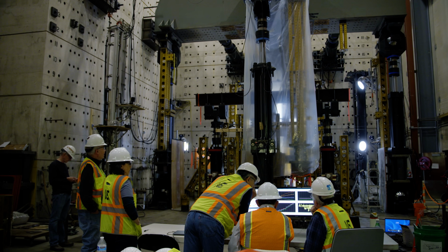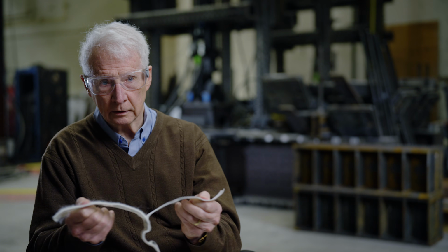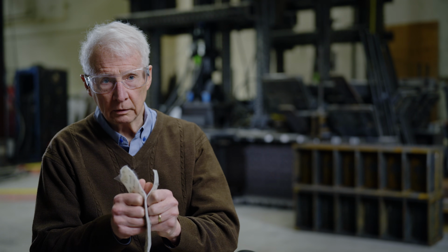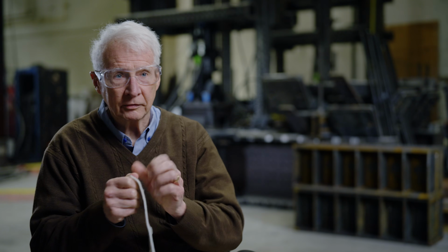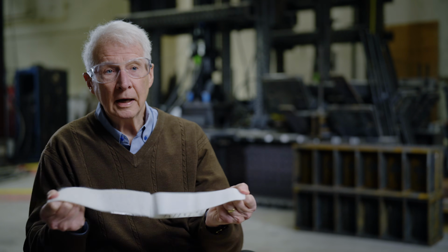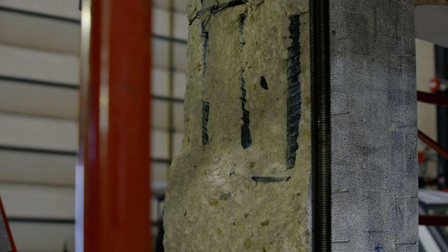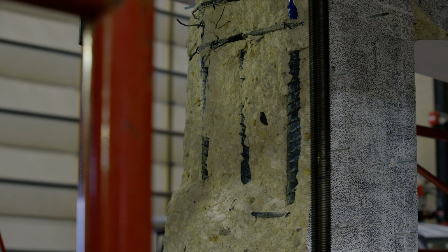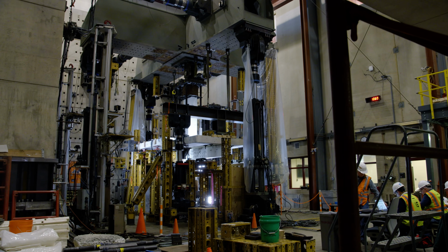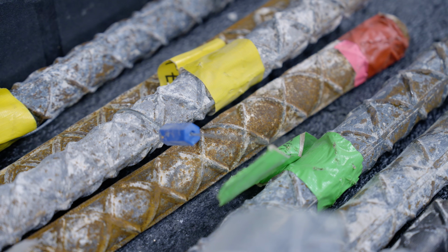When the cement and the water react, it generates a series of chemical products which stick to each other, not unlike the way Velcro sticks together. It is very strong in what we call compression. But the weak link of Velcro is tension. And the same thing is true with concrete. We need to put another material in the concrete which is very good at taking tension, and that is what the reinforcing steel is for.